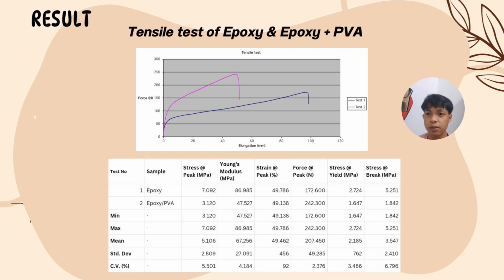For test 1, which is pure epoxy, we recorded a higher tensile strength of 7.09 MPa and a Young modulus of around 87 MPa, indicating the epoxy is stronger and stiffer. However, test 2, the epoxy plus PVA composite, showed a lower tensile strength of 3.12 MPa, but it reached a higher peak force of 242.3 Newton, which means it can absorb more load before breaking, but with less stress.